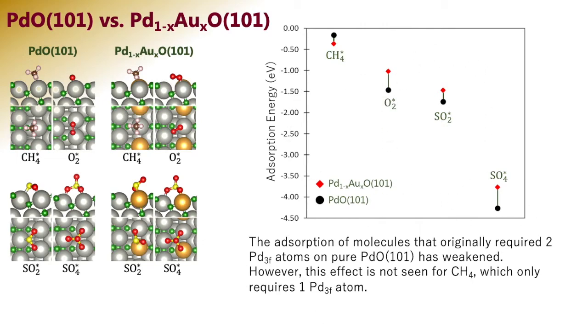Vibrational frequency calculations show the absence of imaginary frequencies for these adsorption structures, while the calculated adsorption energies for methane are in agreement with other studies. As I have shown in the previous slides, an adsorbed SO3 is not thermodynamically favored at typical experimental conditions and is thus neglected in this current work.